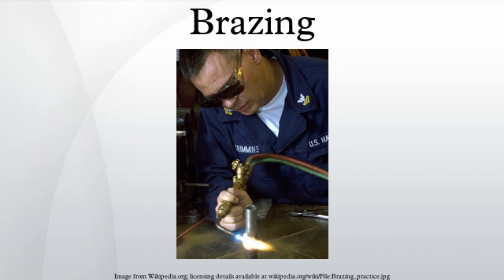99.99% and 99.999% purity levels are available commercially. Care has to be taken to not introduce deleterious impurities from joint contaminations or by dissolution of the base metals during brazing. Melting behavior: alloys with larger span of solidus-liquidus temperatures tend to melt through a mushy state, where the alloy is a mixture of solid and liquid material.